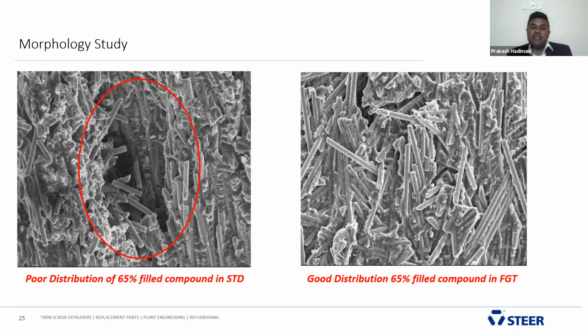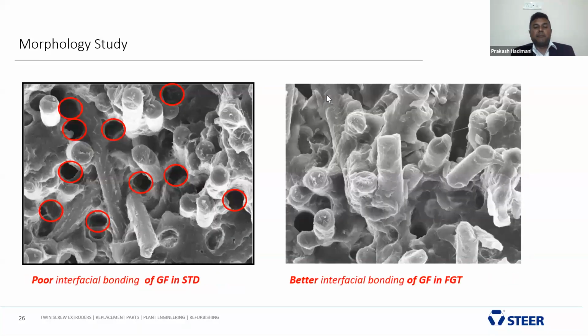On the right-hand side, you see the FGT technology. It uniformly distributed the glass fiber, and the glass is surrounded by the polymer matrix. How did it happen? By using fractional geometry, the DSE stirring elements wet the glass fiber completely, and then the fractional mixing elements retain the fiber, so that it increases the mechanical property. By using fractional geometry like DSE, dynamic stirring elements, and the fractional geometry technology.